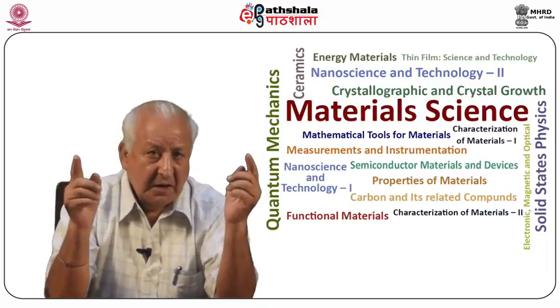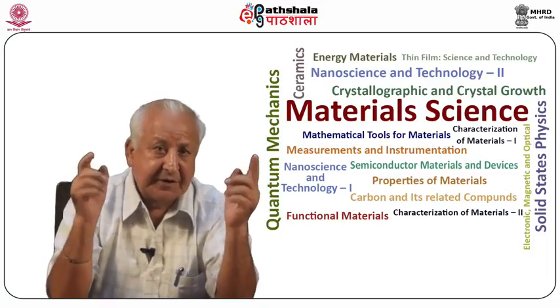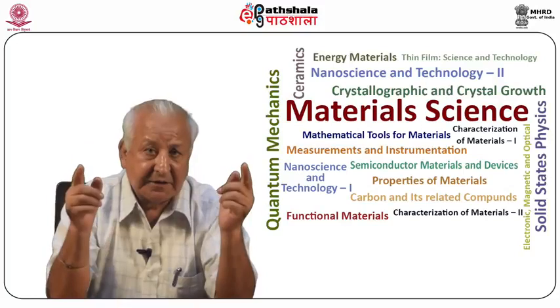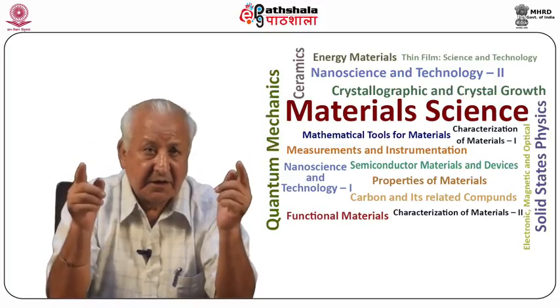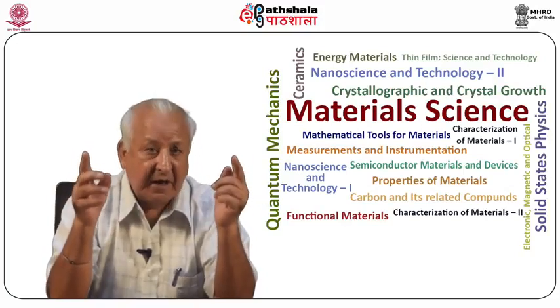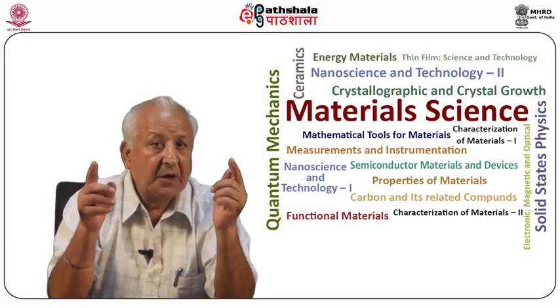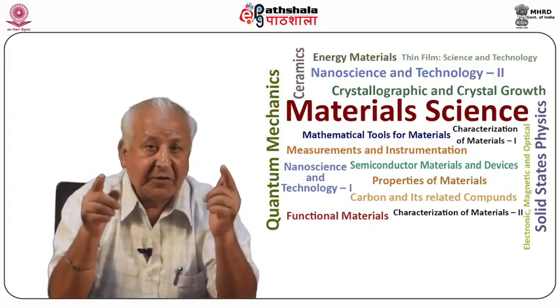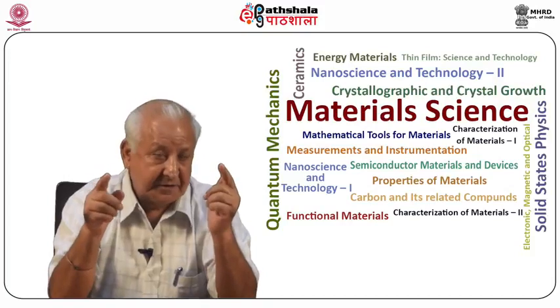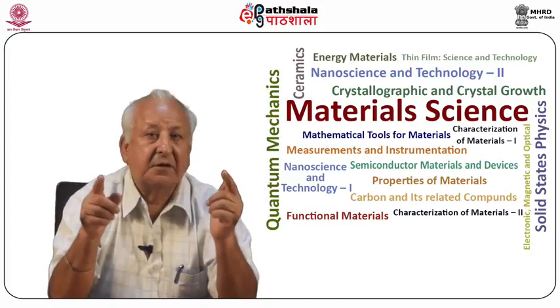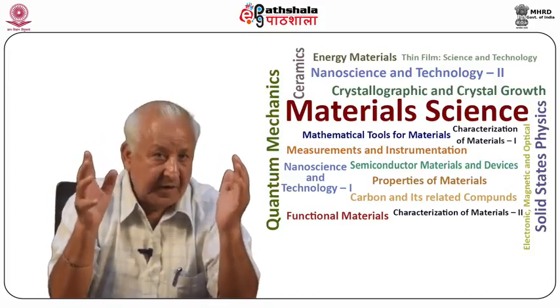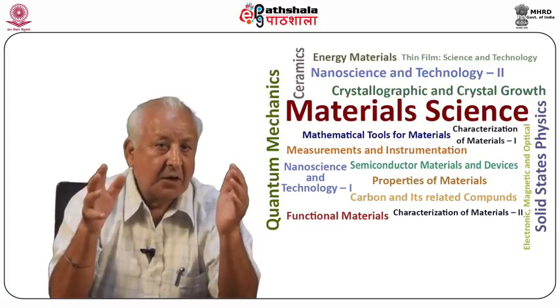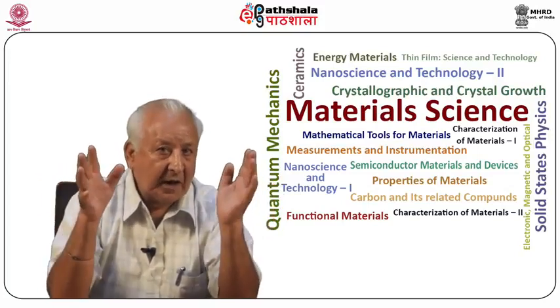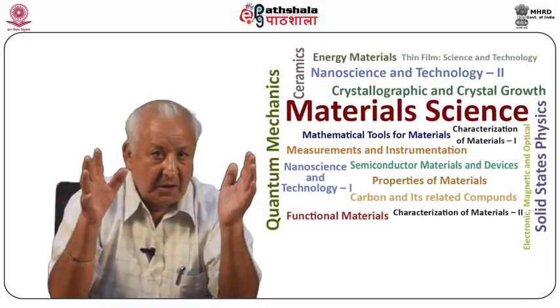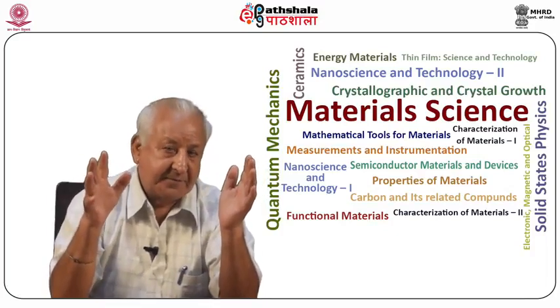Number 1, by addition of suitable impurities like transition element ions with excited energy levels. Number 2, by adding a stoichiometric excess of cations by heating the crystal in alkali metal vapor, followed by quick cooling. The color of the crystal would depend on its nature.